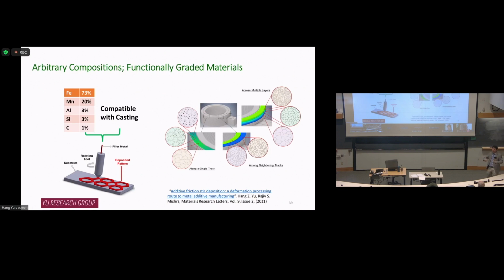In the fusion-based additive process, you need powder, and powder is expensive. It takes time and money to make high-quality powders. In our case, we don't have to. If I have a foundry, cast me a solid bar, and I will do the printing for you. So it's fully compatible with casting. We can try different alloys of interest. We can arbitrarily change the composition and play with that. You don't have to make a powder first. And because of the deformation process nature, you can control the grain size and the precipitates. By controlling the processing conditions, you can make functionally graded material in the future as well.